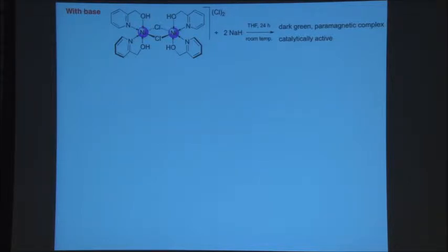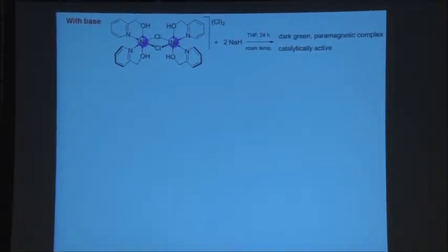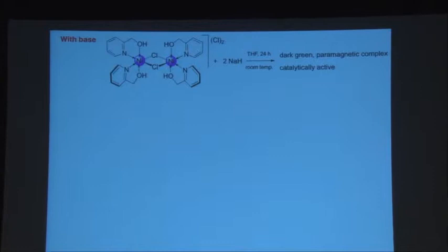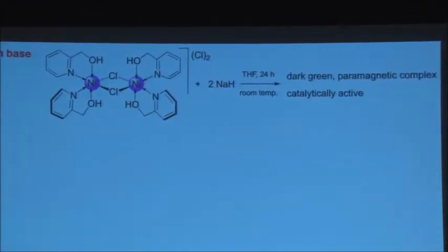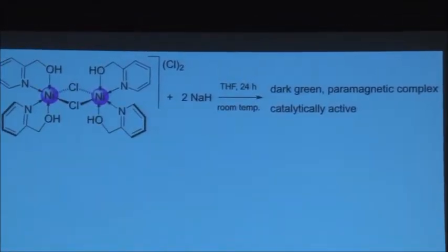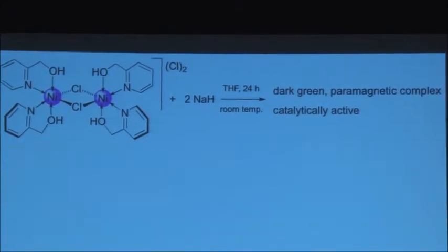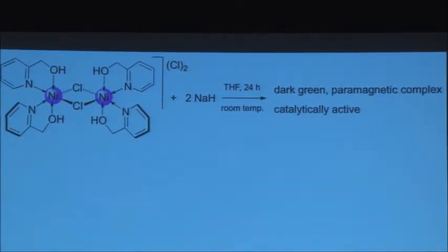So I asked my students to take a strong base, sodium hydride. That's a rather strong base, stronger than sodium hydroxide, to react it with this compound, which is sort of red. Turn dark green. If you want to run NMR spectroscopy, bad news, everything is broad, you see nothing, because the compound is paramagnetic. So then the only thing you have to do is grow single crystals and run to the diffractometer. It took about a year to achieve producing X-ray quality single crystals.